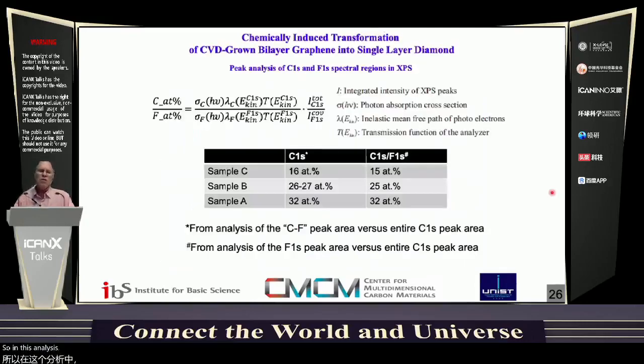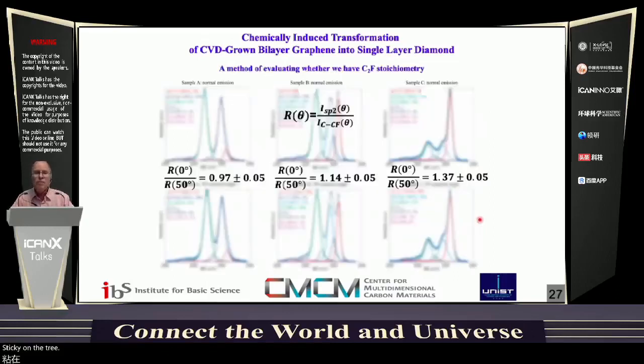So in this analysis, what we're showing is that if we look in the C1S spectral region and we assign the peaks properly, for sample A, we have very close to the C2F 33% that would be perhaps expected. But if we use this ratio of C1S to F1S, we also get a very nice measure of the stoichiometry from XPS alone. And this again is telling us the same story that I just told you, that these two are underfluorinated relative to the saturated C2F, which is the diamond stoichiometry. So this is a further analysis of looking at the tilt at 0 and 50 degrees. And if you get a value very close to 1.00, that's again proving that you have very close to C2F stoichiometry.